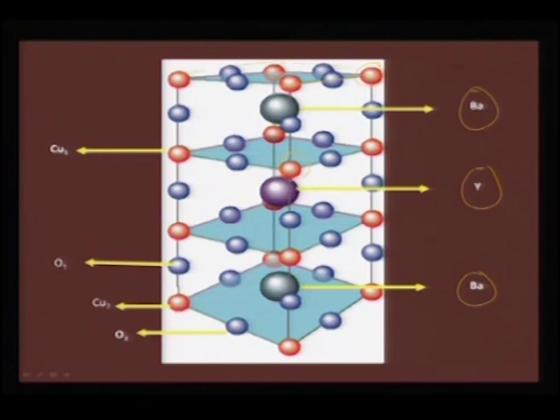So, this is a copper oxygen unit in the AB plane, and you also have a copper oxygen unit in the C axis. So, the coordination of this copper oxygen unit actually is different. In this case, this is of a square planar nature, and this is pyramidal because it is actually getting linked with the apical oxygen. So, 2 types of coordinations are there.